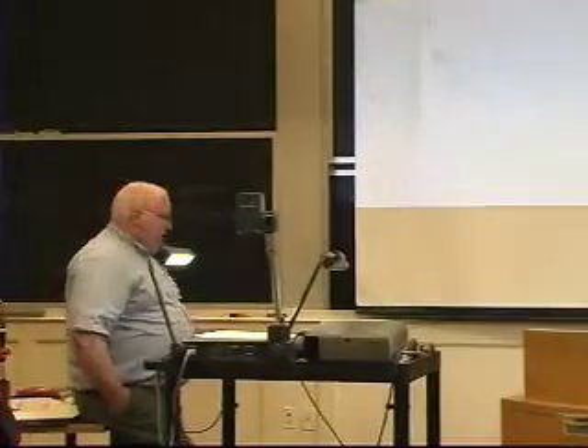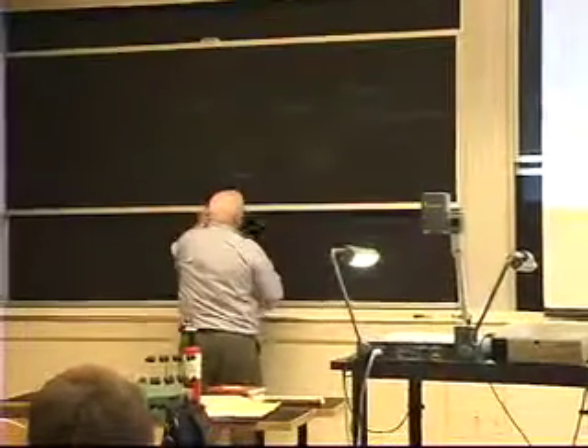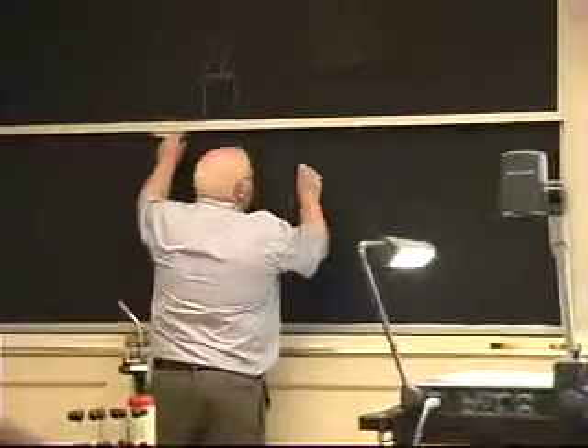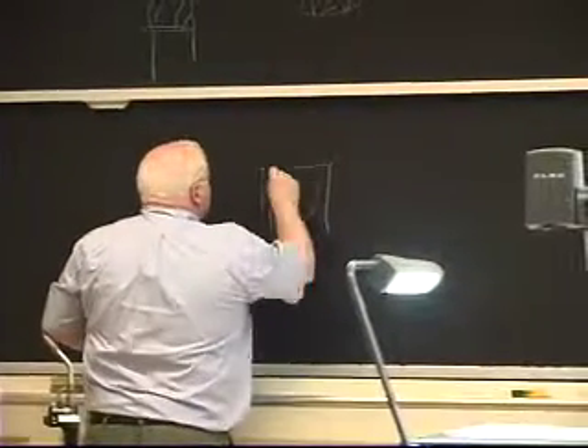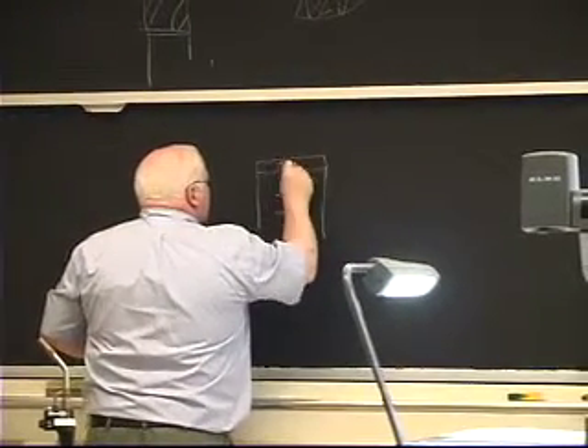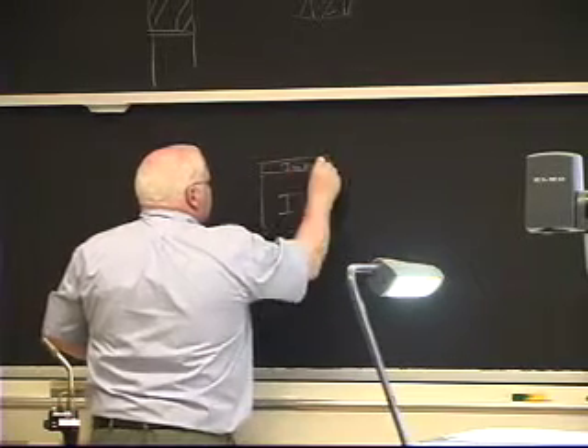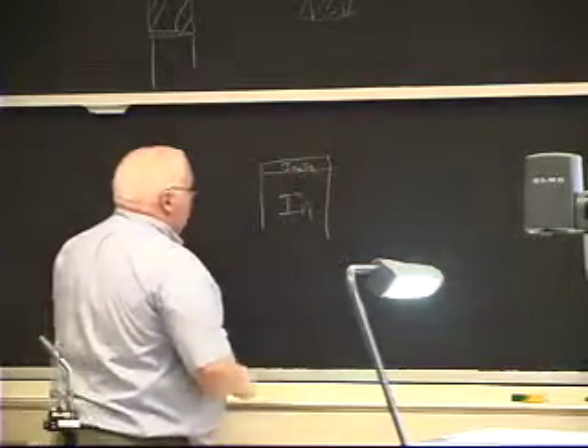So if I'm going to try to roll coat some things, roll bond some things to make something like these bimetallic strips at Texas Instruments, Tylecote and others found that the amount of deformation is proportional to the oxide to metal hardness. Okay? Now the oxide is the contaminant on the surface, right? I've got to get rid of that. And if I'm talking about a very soft material like indium, and it's got indium oxide, In2O3, on the surface, indium oxide turns out to be a very hard ceramic material.